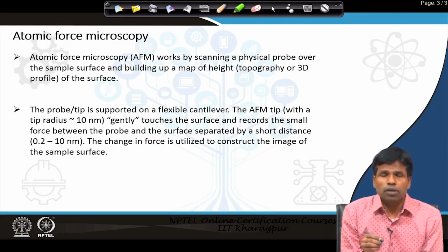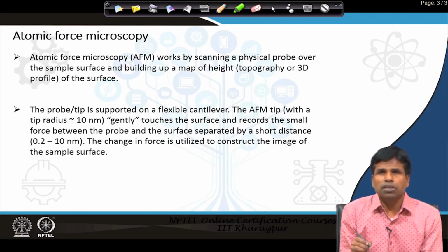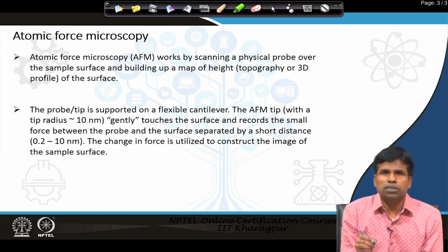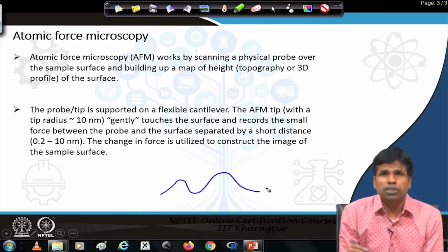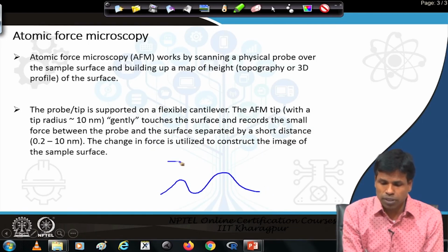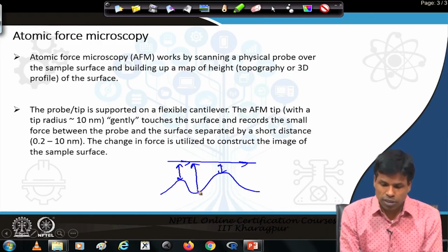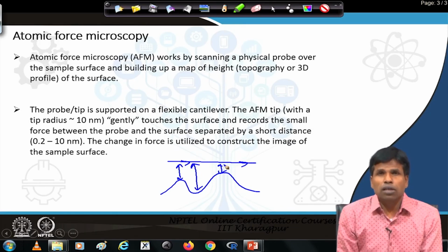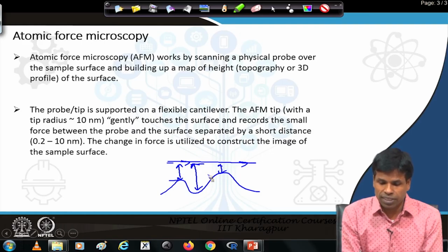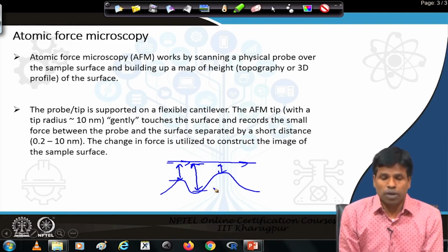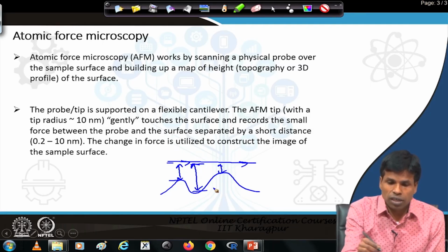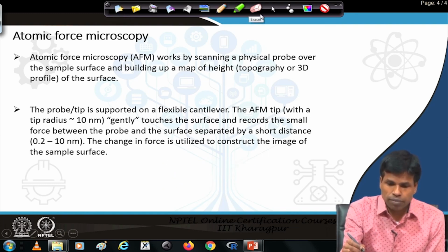Like if we have two different materials on the surface, the force between the tip and one material and between the tip and the other material will not be the same. Similarly, if the sample has roughness, then when the tip is scanned above the sample, the force at different locations will no more be the same. So, by measuring the different forces at different locations, we can construct an image of where there is a small gap between the sample and tip, and where there is a large gap. In this way, by measuring the force, we can create a 3-dimensional image of the sample using the atomic force microscope.